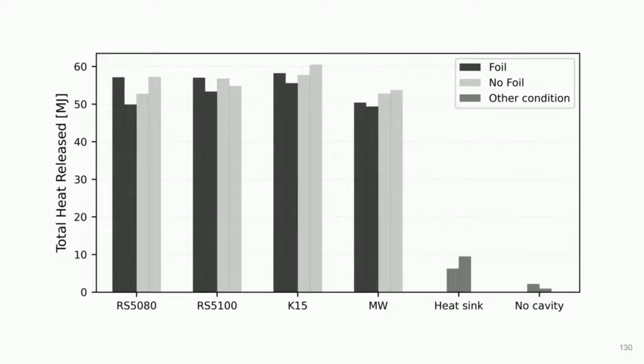You can see that all cases that involve insulation of the cavity are broadly similar, whether the insulation was combustible or not, and whether foil facers were present or not. So for the RS5080, the 5100, the K15, and the mineral wool, with and without foil, you end up with a total heat release that is broadly similar.